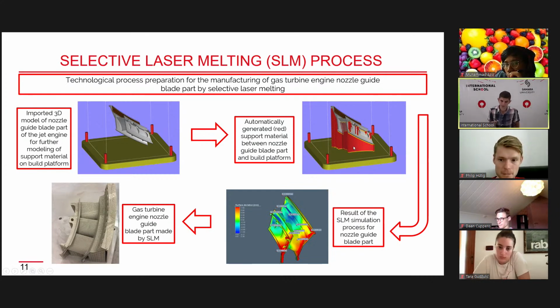But before the printing process, we make a simulation of this 3D printing. You see the temperature comes from the downside to the up. At the top, it's cold enough because it comes to the end of the process. But most energy is applied in the beginning, when the first layer starts to melt, and our laser sends much more energy to that region to create the first layer of our blade. And after that, layer by layer, we achieve our detail. And on the left side, you see the result: a gas turbine engine nozzle with 3 blades, with the difficult geometry deflector inside.